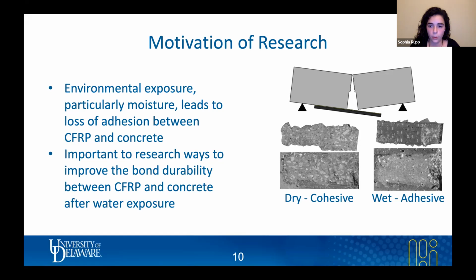Debonding is a very typical failure mode that we see when a strengthened beam is subject to flexure, and it's very undesirable because it happens way before the CFRP can reach full potential and full use out of its properties. So the fact that water exposure can induce this failure mode makes it very important to research ways to improve the bond durability between CFRP and concrete after it's been exposed to water.